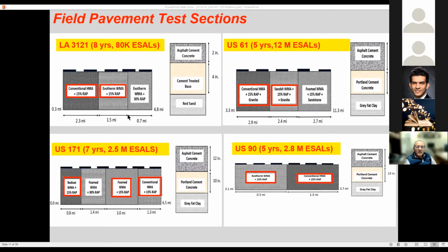And you could see that in each one of those sections, there was a companion conventional mixture. So one can make a direct comparison to the ones that include the WMA additives, which could be of several types. Each section had different additives. For example, 3121 had Evotherm. The 61 had Sasobit and foaming. The 171 had Ready-Set and foaming. And the US 90 had Evotherm. And some of those sites also included an increased RAP content from 15 to 30% in 3121 and route US 171. What you see in here is that some of them were built on composite structure.